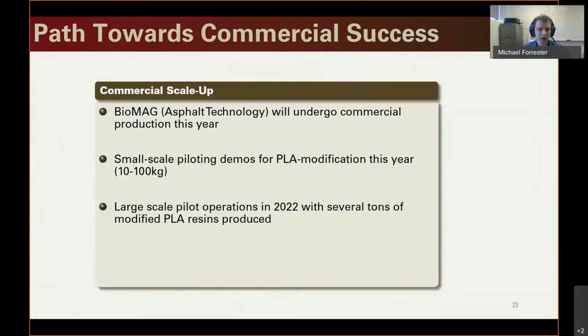So this particular technology is still in the fairly early stages of our commercial process. But we're really hoping to get this to commercial pilot scale this year. Somewhere between 10 to 100 kilograms of resin made, so that we can work with some industry partners and get some prototype samples made. And then the hope is that, after some successful demonstration in 2022, we can actually get to the tons per batch scale, and get this into a lot of different resin formulators and people who would use these parts, to make some pretty cool advances with this technology.